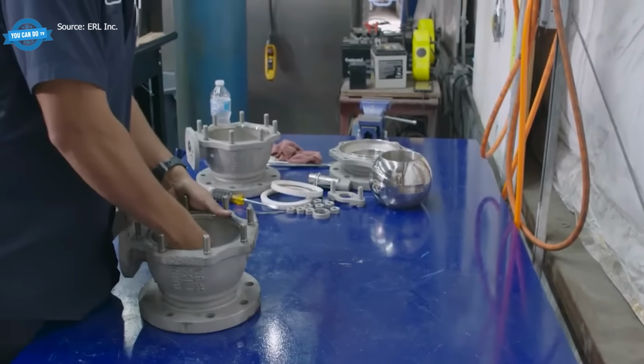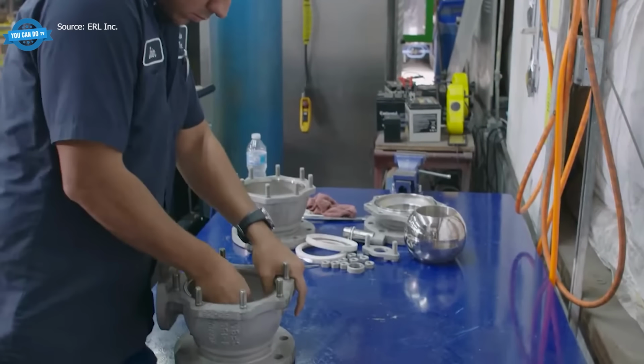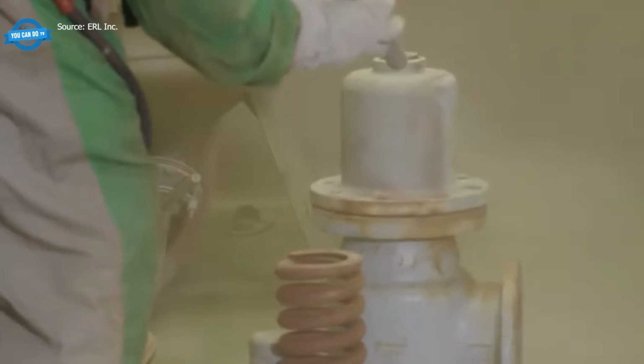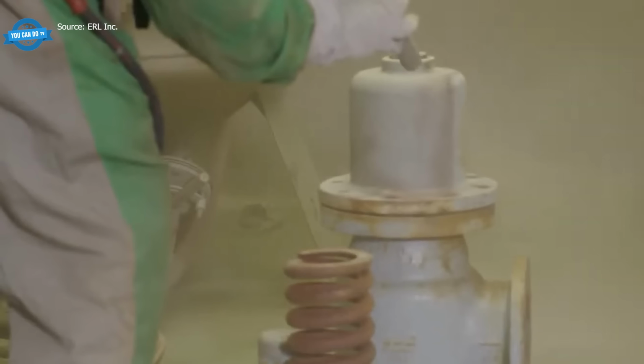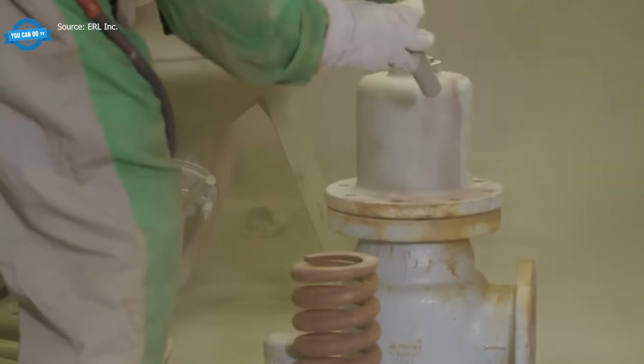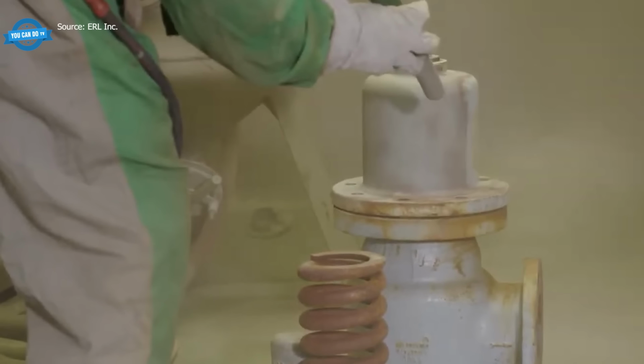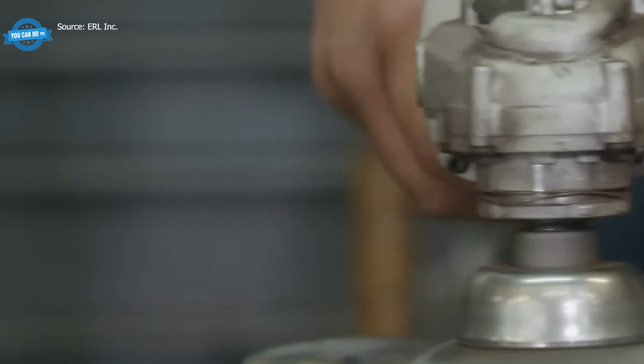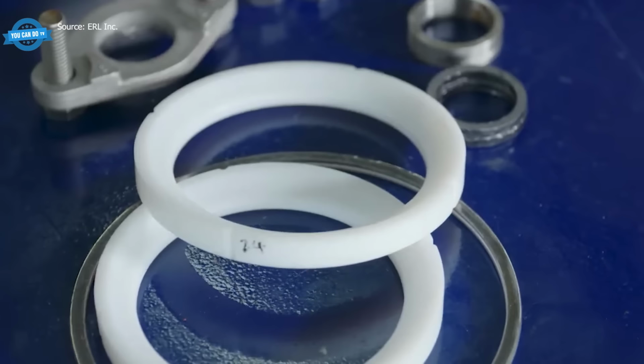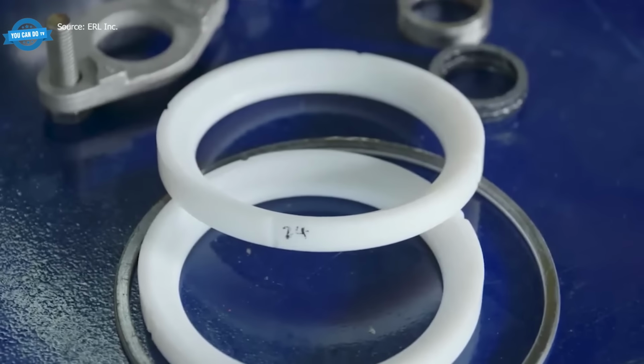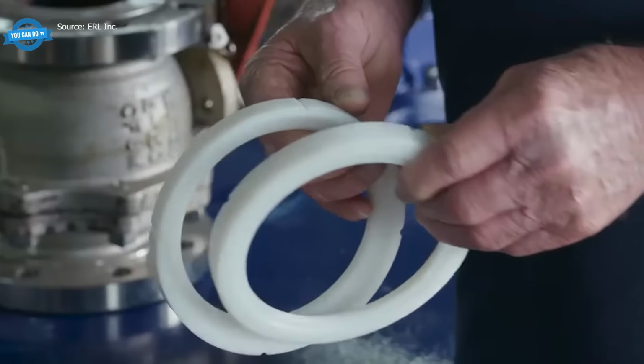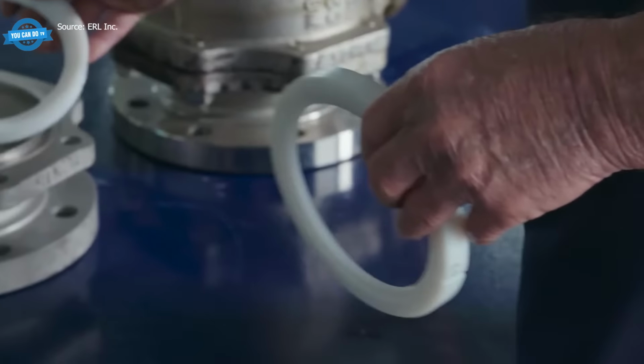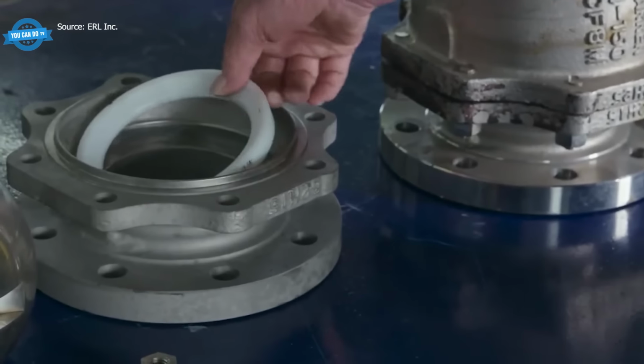Lapping restores a seat that is still salvageable. Most valves arriving for repair need more than that. They arrive locked solid. Stainless and carbon steel ball valves from 2 to 12 inches in 150 and 300-pound pressure classes get sent in for the same recurring failure, product buildup inside the body that freezes the ball in place. The repair sequence starts with full disassembly. Sandblasting the exterior while solvent and wire brushing clean the interior without abrading critical surfaces.